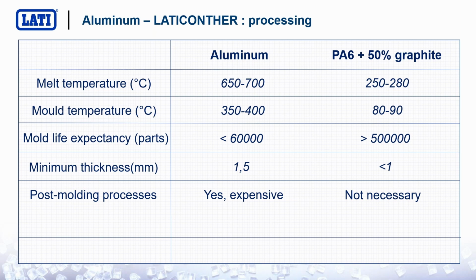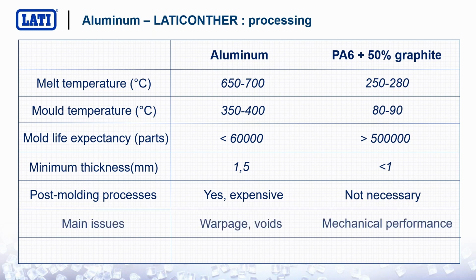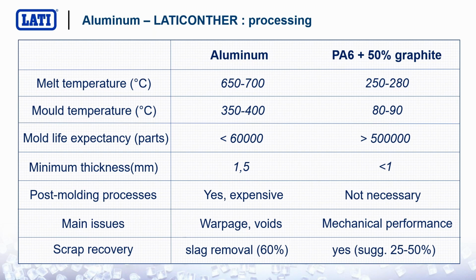You pull out from the injection molding tool, you pull out the finished part. You can have some issues with aluminum, warpage, voids, depending on the way you cool your part down, on the contrary of nylon-based and graphite-based compounds, which can be mechanically brittle. This is the main disadvantage.